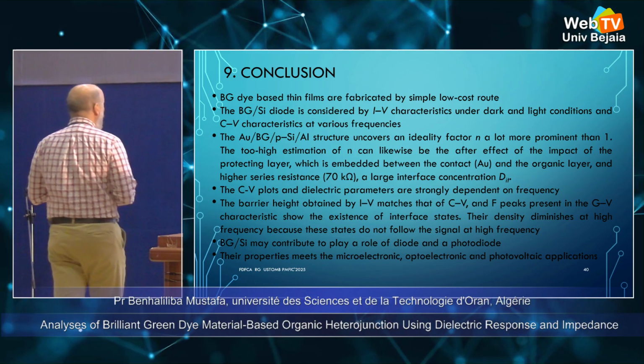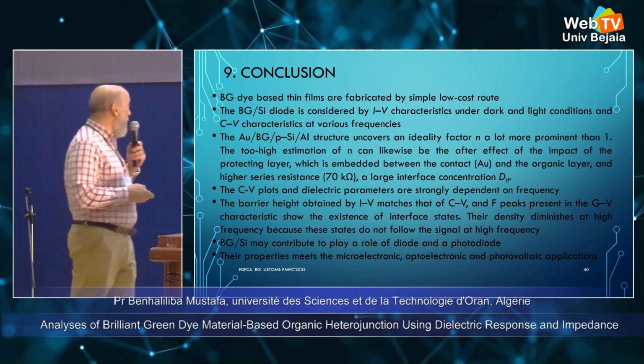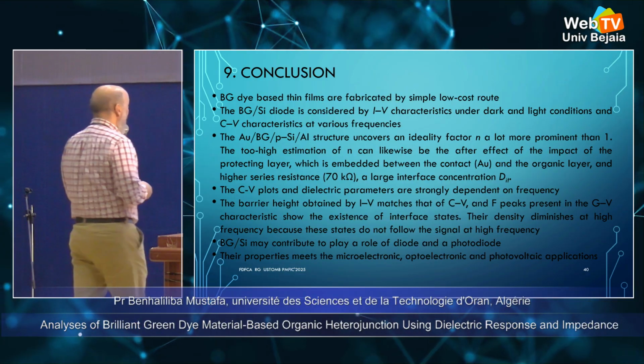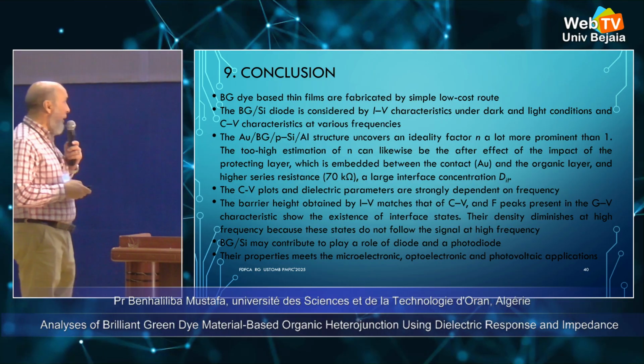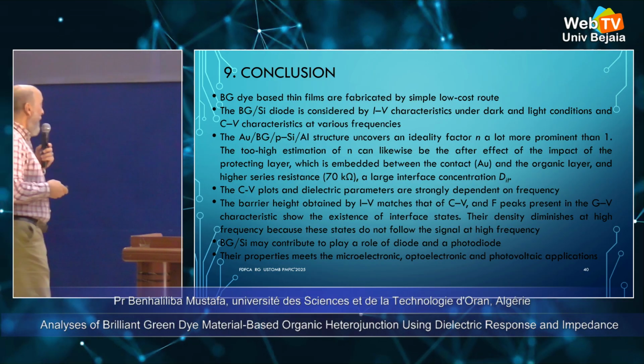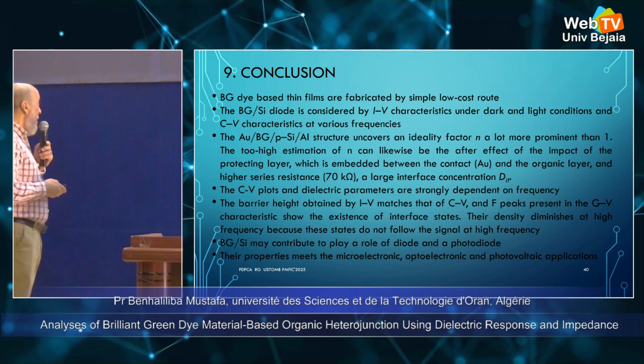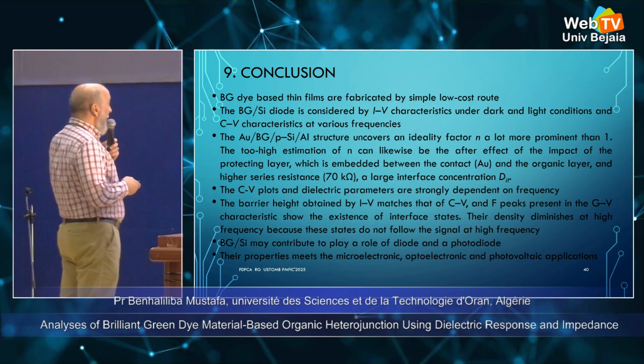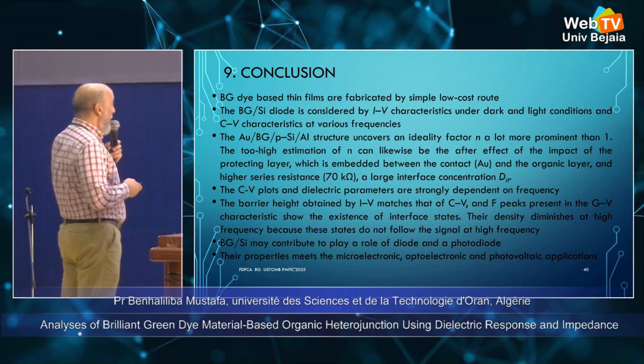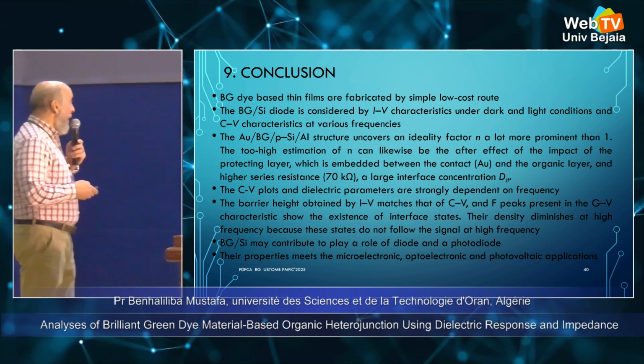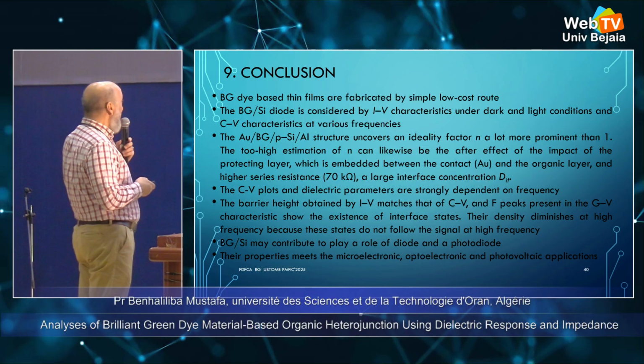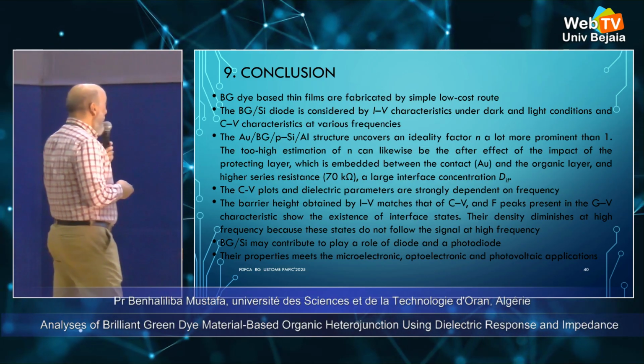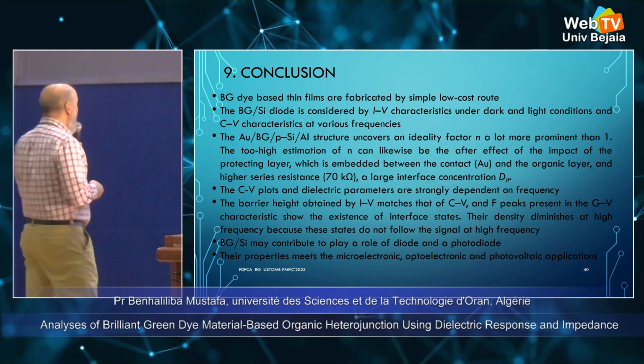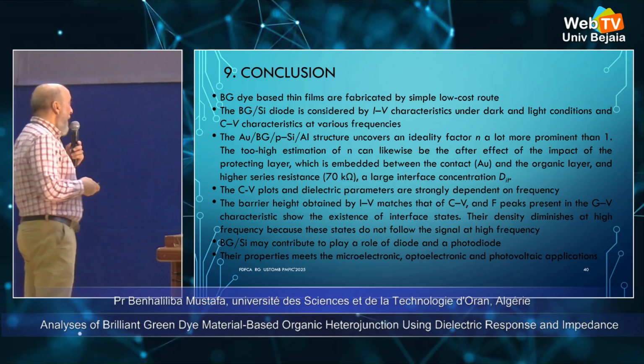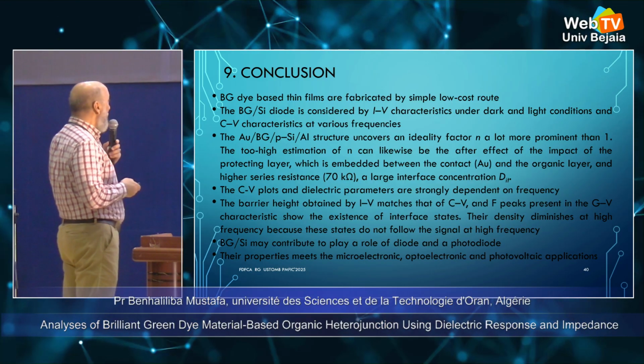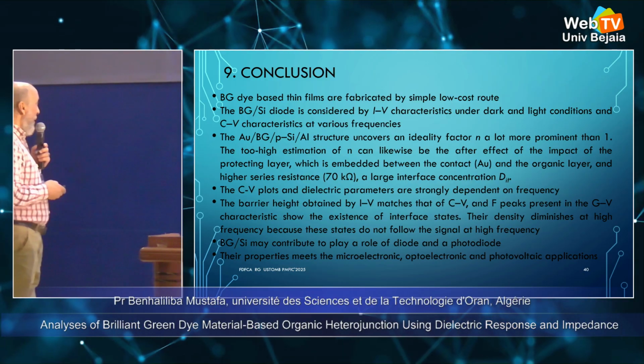As a conclusion, BG dye-based thin films are fabricated by a simple low-cost route. The BG on silicon diode is characterized by current-voltage characteristics under dark and light conditions, and CV characteristics at various frequencies. The structure based on BG reveals an ideality factor n much greater than 1. The too high estimation of n can also be the effect of the insulating layer embedded between the contact and the organic layer, and a higher series resistance of 70 kilo ohm, and a large interface state concentration. The CV plot and the electric parameters are strongly dependent on frequency.